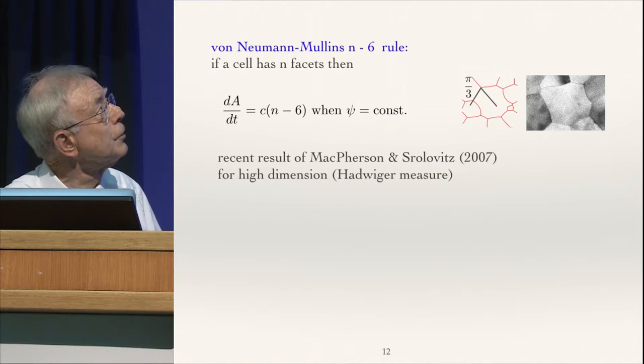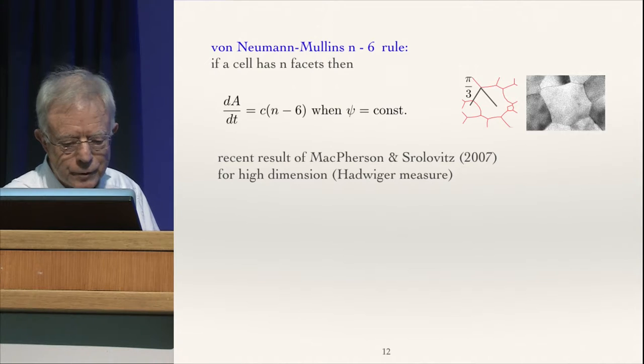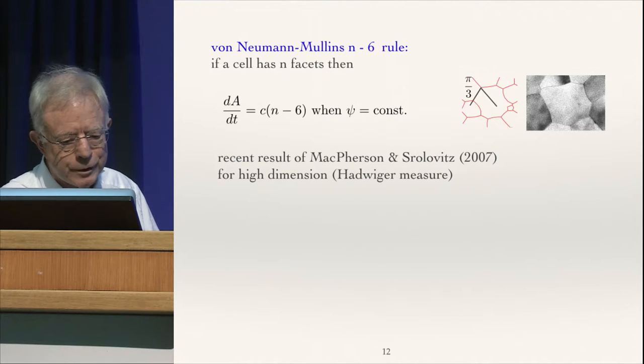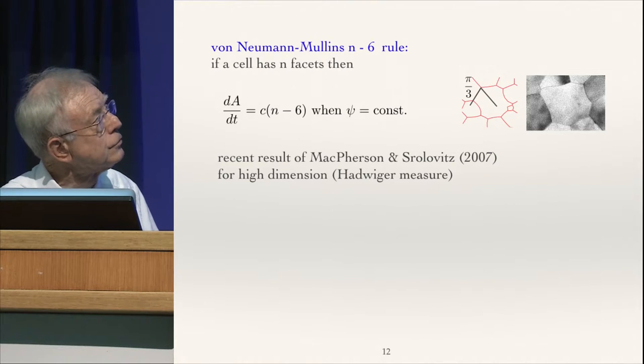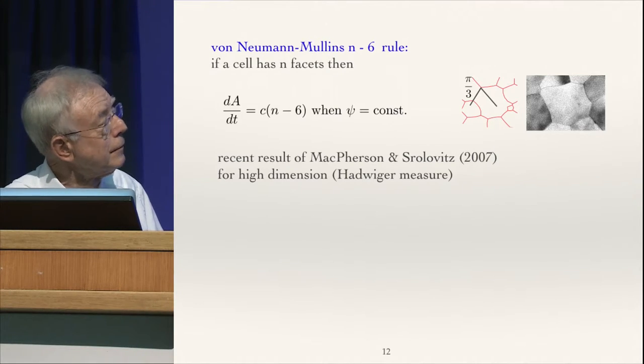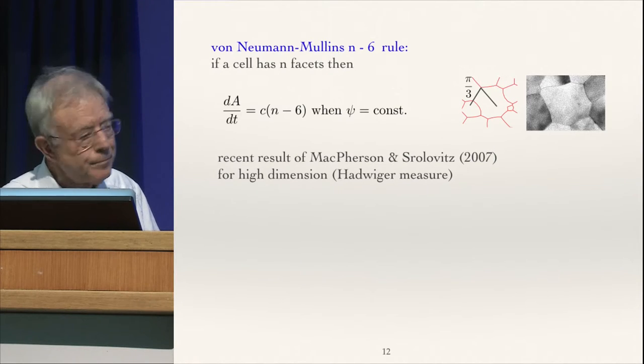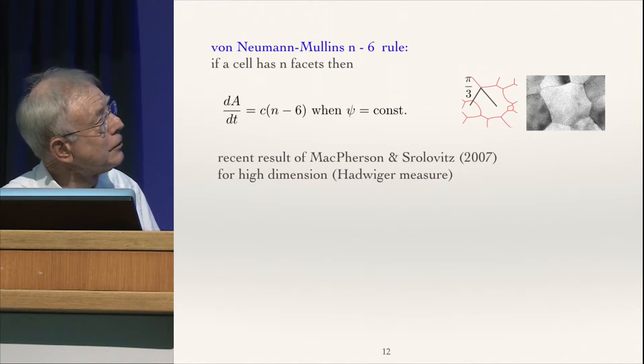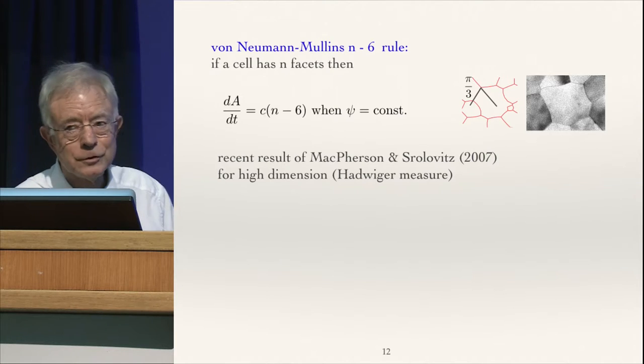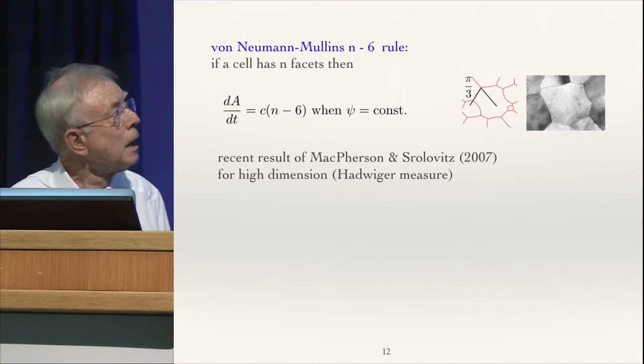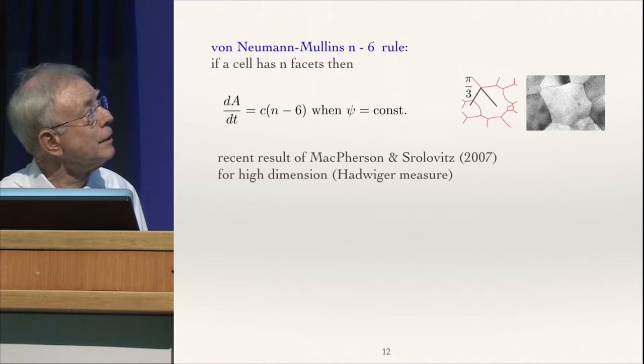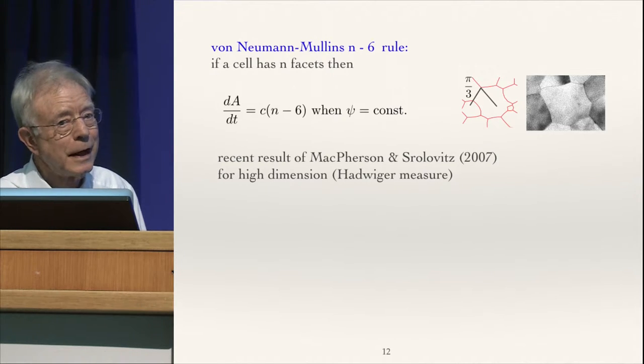First, I'll tell you the so-called von Neumann-Mullins n minus 6 rule, which is that in the case when the energy density is constant, like in a soap film, then the rate of change of area, dA/dt, is some number which you just calculate, like 2 pi over 3 or something, times n minus 6, where n is the number of facets. And you do this just by integrating. You write the dA/dt, and you just integrate it around the boundary and take account of the jump, and that's it. And there's a new result from 2007 of McPherson, Professor Bombieri's colleague, and Srolovitz, which proves this for high dimension and is extremely deep using a Hadwiger measure. It's very, very interesting. It solves an issue which had been dangling for 50 years.